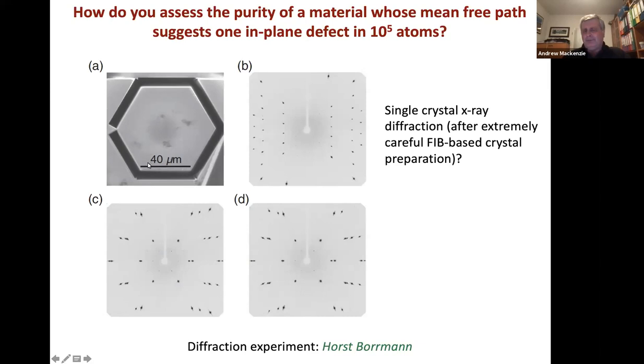If we prepared the crystal extremely carefully using a FIB to avoid it being damaged and getting lots of mosaic spread just from the way it was handled, then you can take his word for it that these are single crystal oscillation data where he's measuring rocking curves and everything, and there's nothing at all in any of those diffraction patterns to indicate that the crystal is anything other than perfect to within the resolution of that experiment. So there's simply no chance of using X-rays to get information at this level.